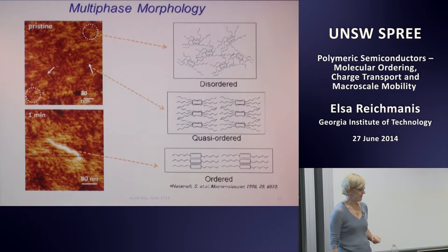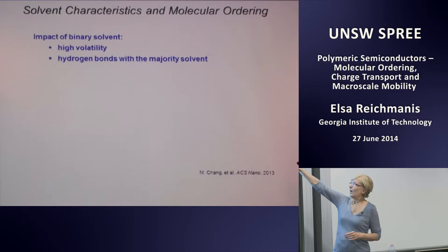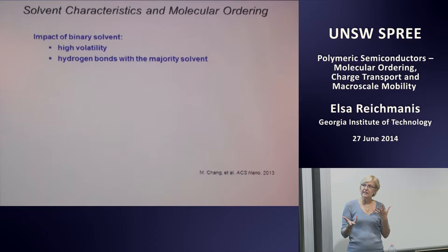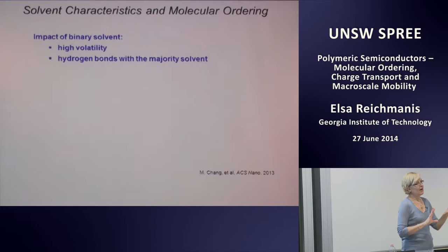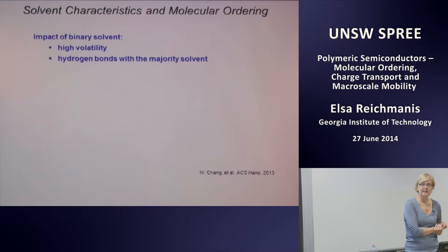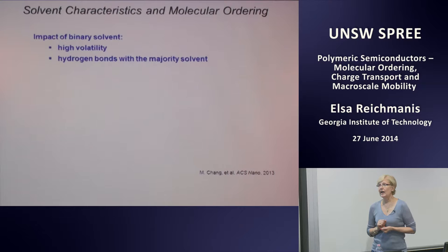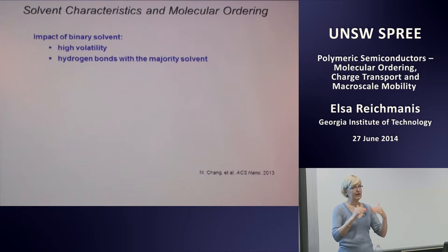All right, it's also possible to do that by using a binary solvent system. In particular, if that binary solvent is selected from a number of solvents that have relatively high volatility, but can also undergo hydrogen bonding. The importance of the hydrogen bonding interaction is that the solvent system can form an azeotrope that is higher boiling than either solvent alone, and as solvent evaporates during the deposition process, the boiling point of the remaining solvent increases as the solubility of the polymer in that solvent decreases.